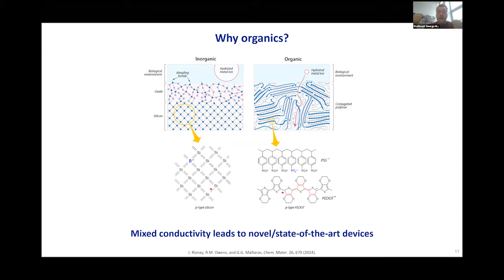So you want to have these carriers interact as much as possible, as strongly as possible, in order to transduce phenomena in the biological world. For example, if this ion is set to motion, you want it to couple with an electronic charge inside your transducer, so that by looking at the motion of this electronic charge, you can tell that this ion has moved and infer that a neuron has fired. If you try to do this coupling by using silicon, you find that there is an oxide or a nitride at the interface that protects silicon, but serves to space away the two carriers from each other. And as a result, it decreases their interaction. So the coupling between ionics and electronics is very poor in this case.